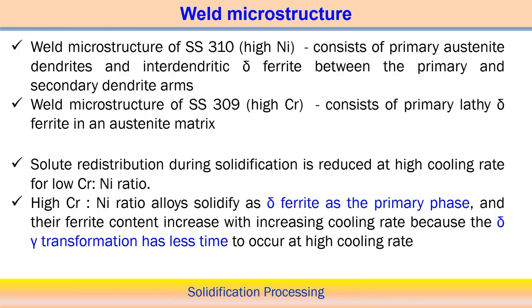Now we can also see the fusion welding microstructure of SS310, which means stainless steel, particular grade 310. Usually in this case the nickel content is high. We know that chromium and nickel content is usually high in stainless steel, but in SS310 the nickel content is high as compared to SS309. So when nickel content is high we can expect the structure to consist of primary austenite dendrites, and the interdendritic space is delta ferrite. Delta ferrite is the high temperature phase, so the interdendritic space is occupied by delta ferrite, but the primary dendrites are the primary austenitic dendrites. And between the primary and secondary dendritic arms it is filled by delta ferrite.